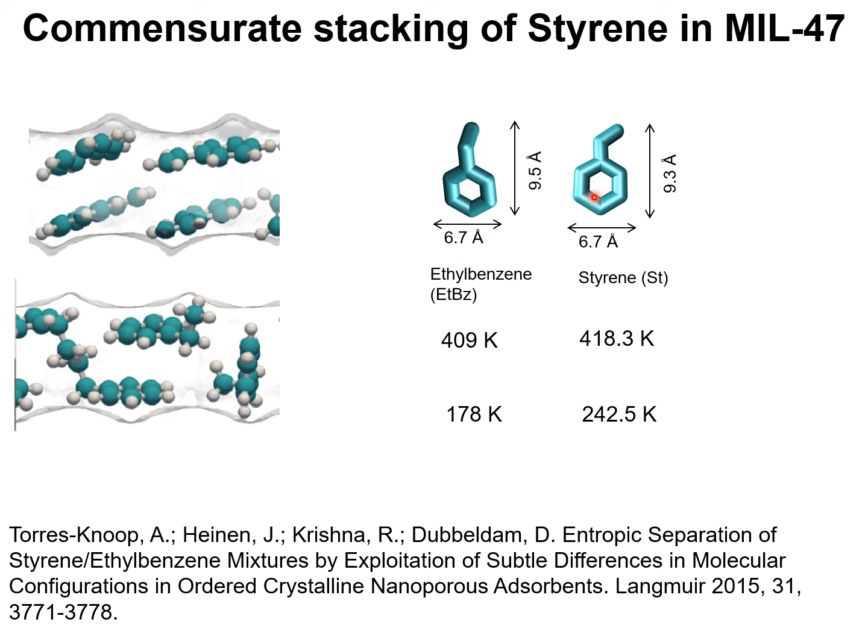The difference between styrene and ethyl benzene is that styrene is a flat molecule, and within the 8.5 angstrom lozenge-shaped channels of MIL47, we have a commensurate face-to-face stacking of styrene molecules, whereas for ethyl benzene, the side chain, the ethyl chain, is not in the same plane as the benzene, and the stacking of ethyl benzene within the channels is less efficient.